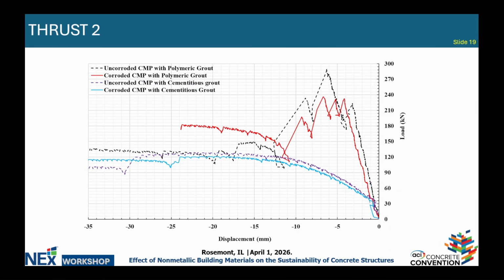And you also look at the possibility of energy dissipation in the polymer concrete grout, which are those top 2 curves here, whether corroded or uncorroded. You do see in the red line a reduced load capacity with the corroded, not being as comparable to the uncorroded, but still you have that energy dissipation being carried forward into the ultimate deflections that you see.